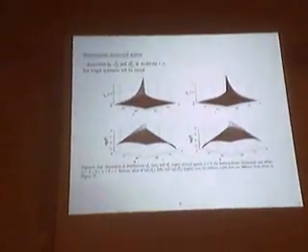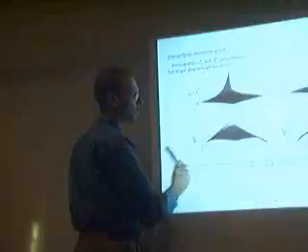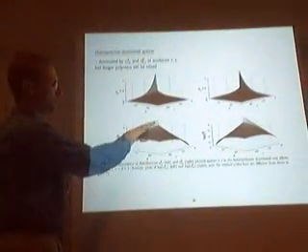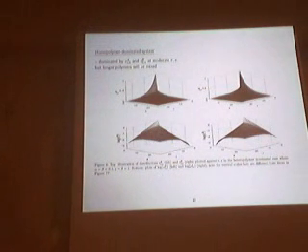Then you tend to get homopolymers, but only at the shorter lengths, because if you still have these KBA and KAB non-zero, then after a certain number of A's, you get a long sequence of A's, but eventually you probably get one of the opposite ones formed. So you get these very broad distributions. These distributions have two sorts of features. At short lengths you get homopolymers, but later on polymers get so long that you tend to get crossovers.